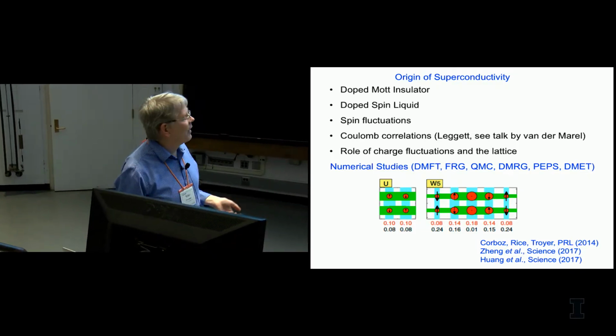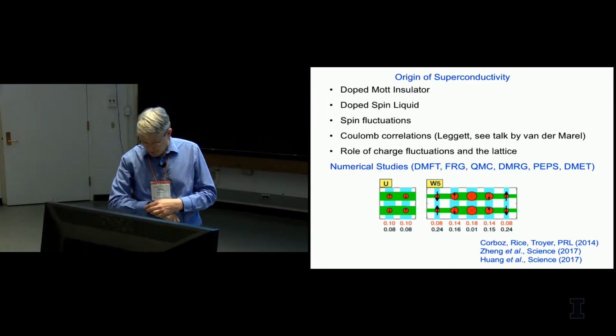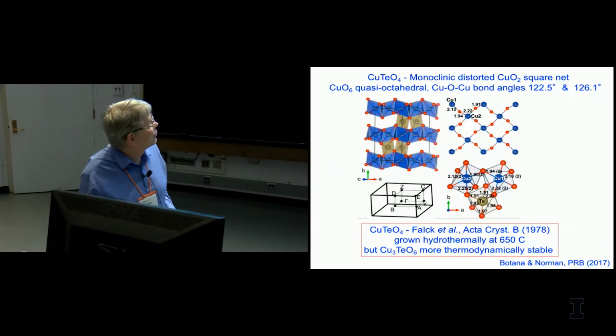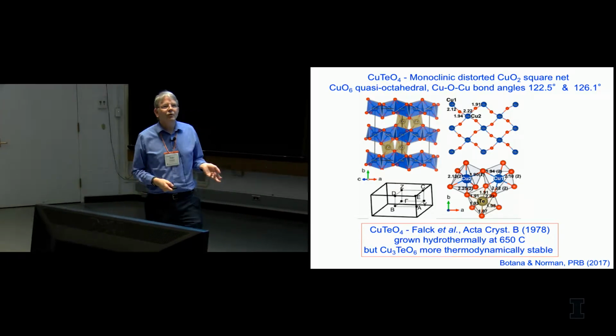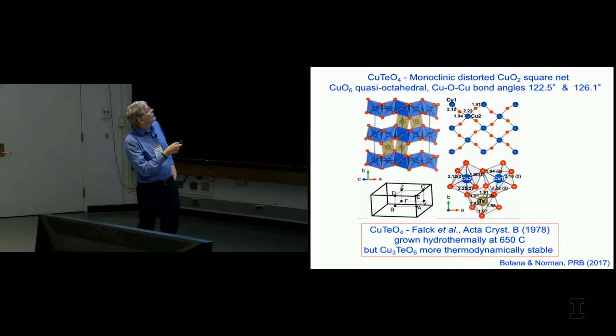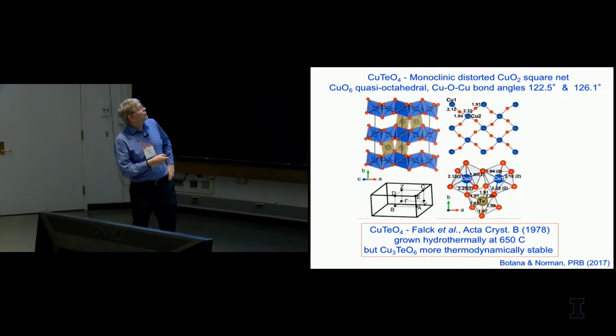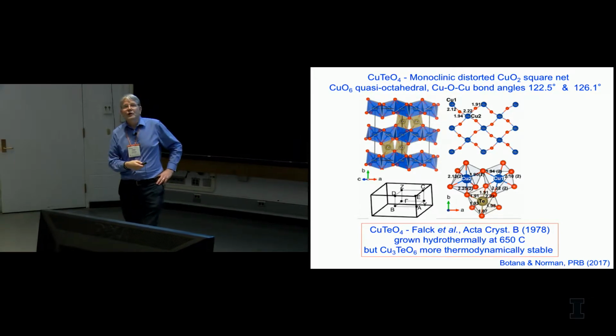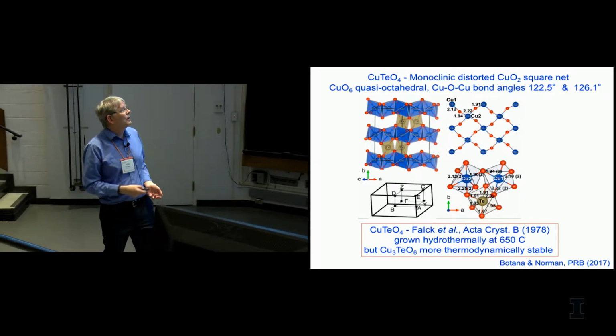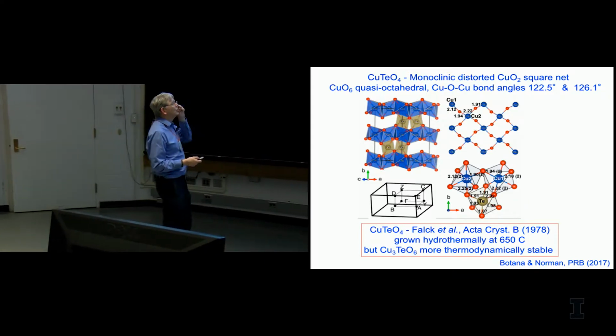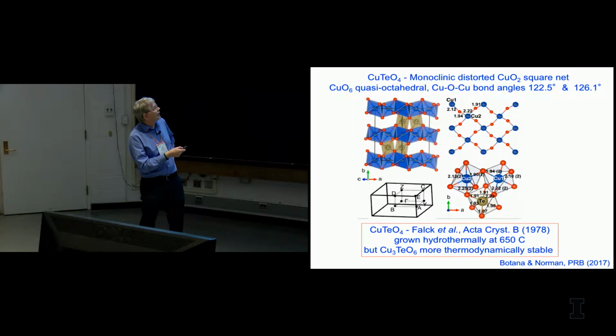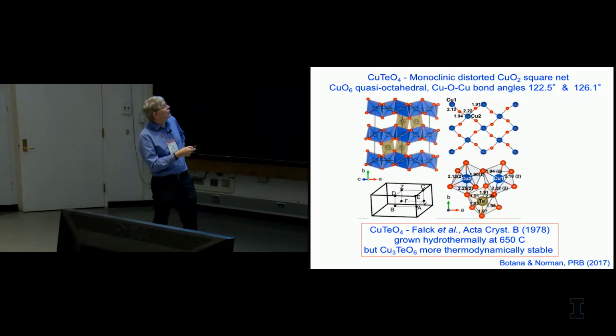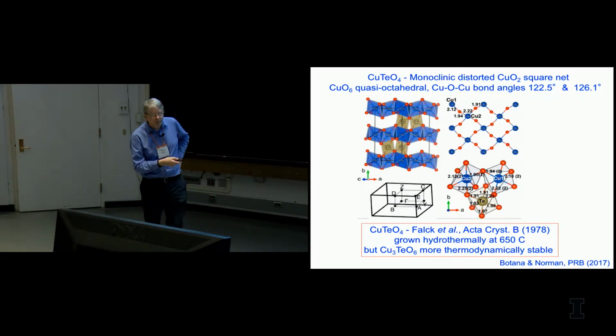So imagine you think, like Phil, that superexchange is actually what's causing the pairing. Is there something else that we can do? And the answer is yes, maybe if we could find cuprate analogs which differ enough from cuprates that could tell us whether we're on the right track or not. So have all the square planar cuprates that you know been made? And the answer is no. There's this material out here, one report in the literature from the 1970s, hard to grow hydrothermally at high temperatures, but this material actually is interesting in that the copper-oxygen bond angles are about 120 degrees. So if a superexchange interaction was evident, this type of material should have a strongly suppressed superconducting transition relative to square planar cuprates which have 180 degree bond angles. More or less also the coppers are in a near octahedral coordination.